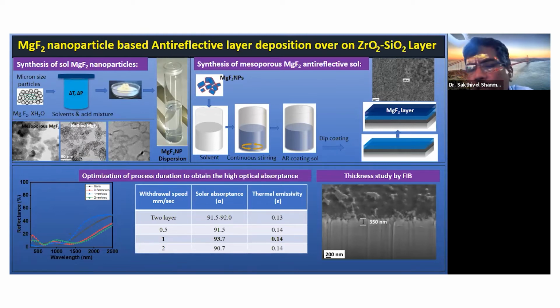So this is a very unique way we developed nanoparticles. Most of you know how nanoparticles are developed by various processes. There are two main routes: a step down and a step up process. In the process we used, we take a very cost effective commercial micron size particle, magnesium fluoride, which is available in the market, and we convert the micron size magnesium fluoride particles into very fine, uniform, hollow porous nanoparticles.